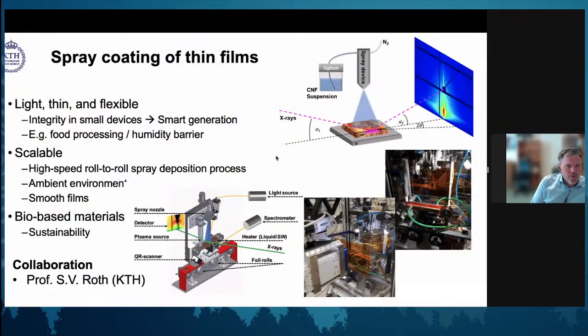So we have been working a lot with spray coating. And the starting point of that is Professor, since last week, Professor Stefan Roth at KTH, who has been the starting point for trying to do spraying for making coatings of, for example, bio-based material. And the cool thing with spraying is, of course, you can provide barriers. The good thing also is that it's a roll-to-roll industrial process. So it actually is quite scalable. If you can succeed in the lab, it's not too far away that you can make larger areas.